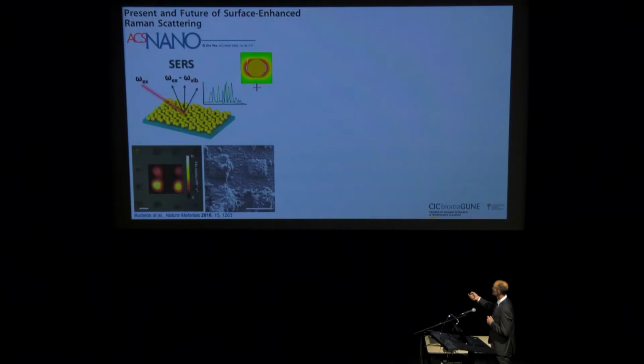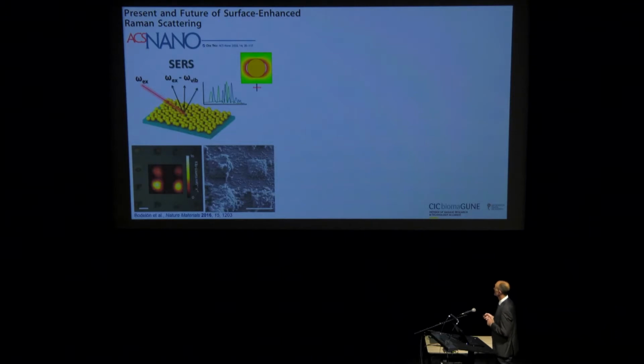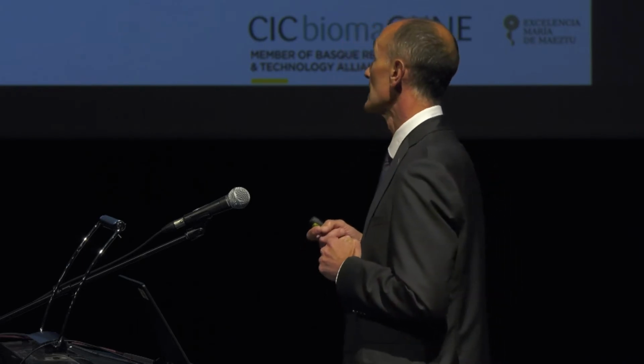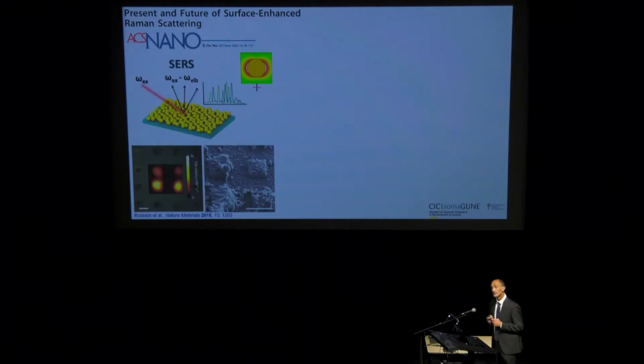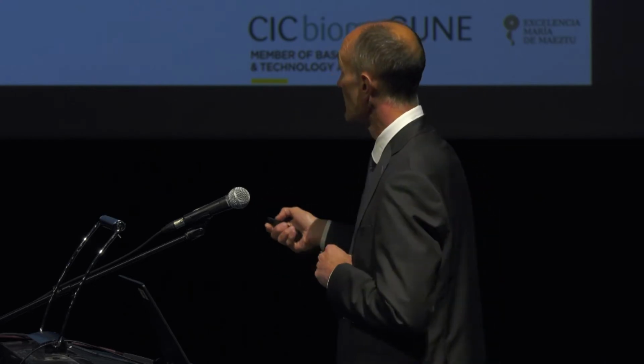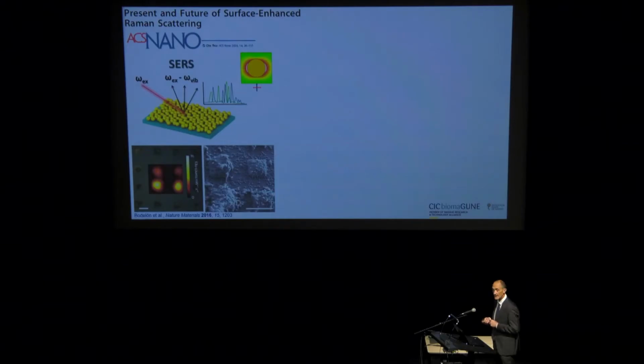So then Raman scattering becomes not only highly selective, but also extremely sensitive. So you can use this technique to identify even the presence of single molecules in a system. And so we have been working largely on this topic. One example is shown here where we used arrays of gold nanorods to amplify the Raman scattering signal of molecules that bacteria use to talk to each other. So these are biomarkers which are specific of the communication between bacteria. So by using these islands where we have the nanoparticles, we can really obtain the signal of these biomarkers so that we can understand how bacteria behave.